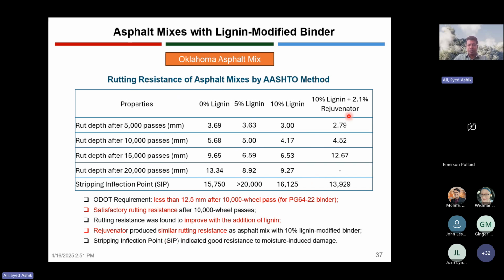The mix with 10% lignin and rejuvenator also produced almost similar results until 10,000 passes, but after that we have seen some significant increase in the rutting. So that could be an issue with 10% lignin with rejuvenator. In stripping inflection, if we look at the stripping inflection point to understand the moisture resistance of these mixes, all of these mixes did a pretty good job. They showed a very high stripping inflection point. The 5% lignin was more than 20,000. The 10% lignin was almost 16,000 wheel passes. And the 10% lignin with 2.1% rejuvenator was around 14,000 wheel passes. So moisture-induced damage wise, almost all the mixes did pretty well.